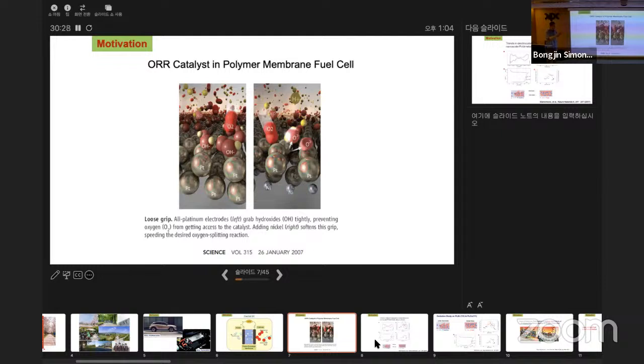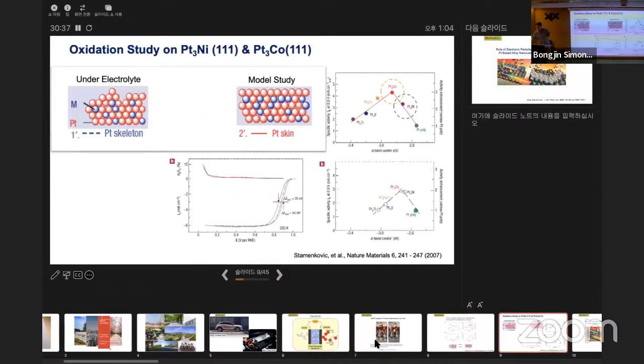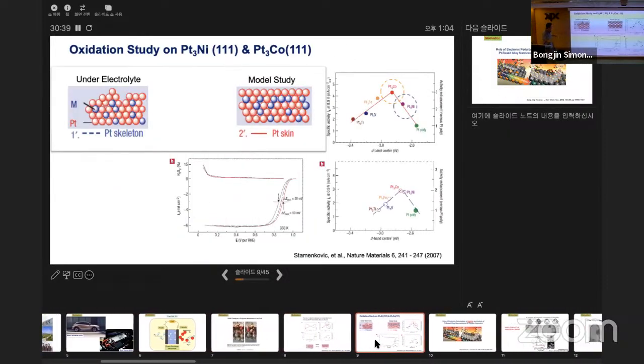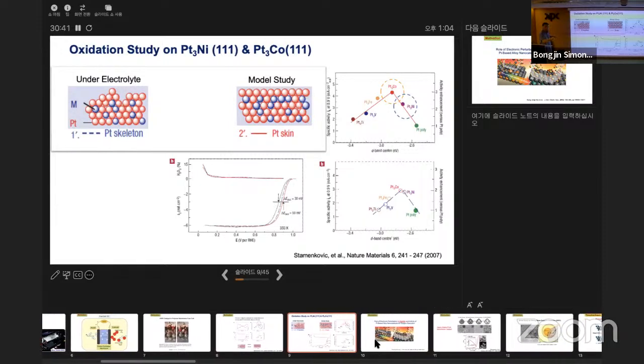So with the different electronic structures of platinum-3 nickel and platinum-3 cobalt, they were able to mimic what is actually happening in electrolyte. Once you put a nanoparticle into the electrolyte, every transition metal on the surface is being melted. It's all gone. And you're going to have this kind of skeleton surface on top. And this one is very difficult to model.